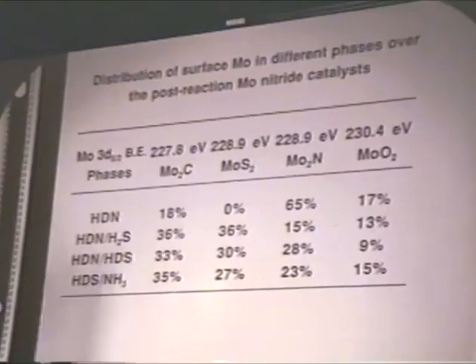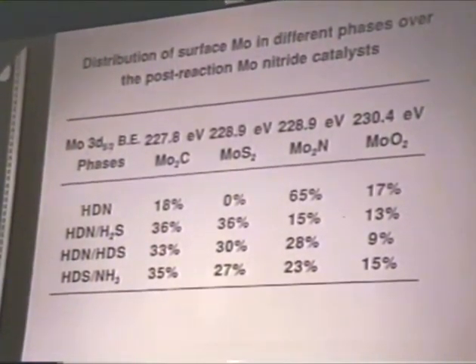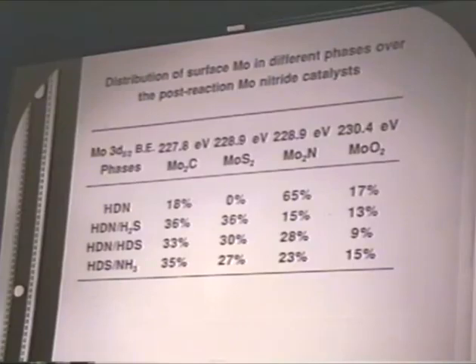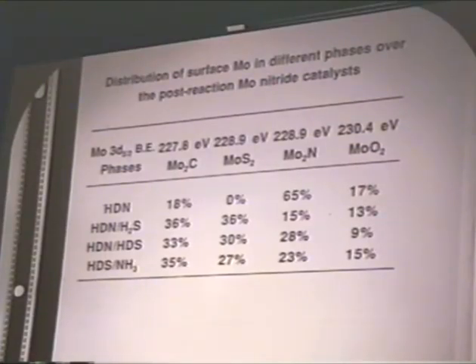Now, using this additional information, we have made some rough estimates. I'm saying a rough estimate because, as you notice, the binding energies for molybdenum 3D 5/2 for the sulfide and the nitride phases is the same. So we have done the approximation using the amount of sulfur calculation from the sulfur 2P region. Based on that, here's what we see.